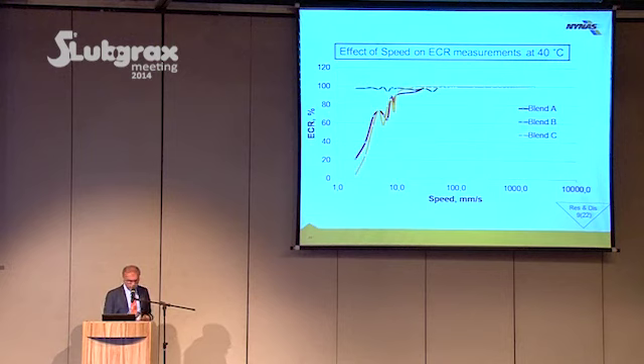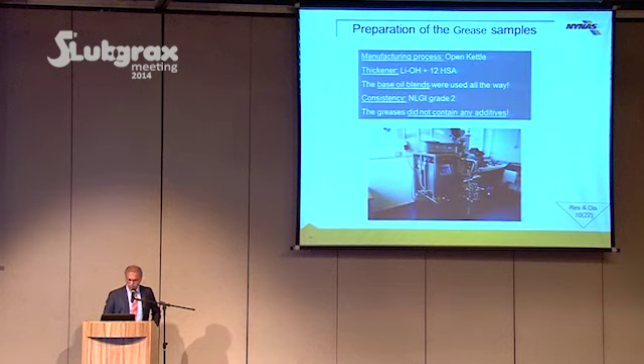So what we saw is that at lower speed, in fact, blend B outperformed the other 2. Here we see that the film breaks down at lower speed, but blend B, which contains group 2 and naphthenic, continues to be stable. Okay, now we move to greases.